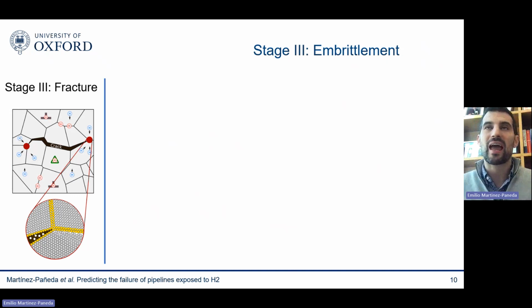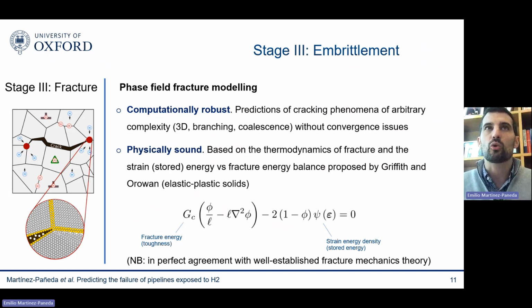That takes me to the embrittlement part. So now I know how much hydrogen I have, where and when. I need to predict when cracks will nucleate and grow. For that, what we use is the so-called phase field fracture models. And we use this for two reasons. The first one is that they're computationally very robust. No matter what the complexity of your cracking problem is, whether you have 3D cracking problems, branching, coalescence, you can capture that without any convergence issues. So it's computationally very compelling.